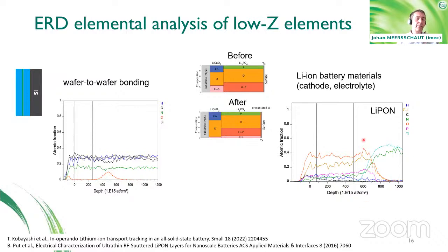And you see here that with elastic recoil detection analysis, we are very well capable of mapping the depth profile of the different constituents like lithium, hydrogen, nitrogen, and phosphor in these electrolyte materials. And it helps us by understanding which materials are where, it helps us to further develop these technologies.